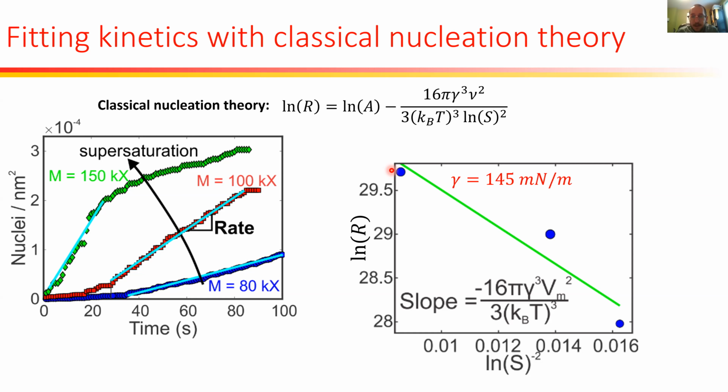Yes. So yeah, you're right. I kind of see what you're saying now. So we go from this constant nucleation regime back to a flat one. And that's because we've decreased the supersaturation of the solution enough now that there is no driving force for nucleation anymore. Instead, we just have crystal growth occurring, because that's a very low activation energy process. Yeah.